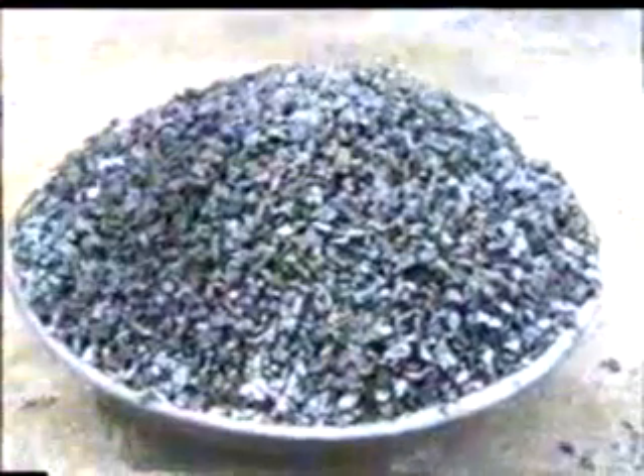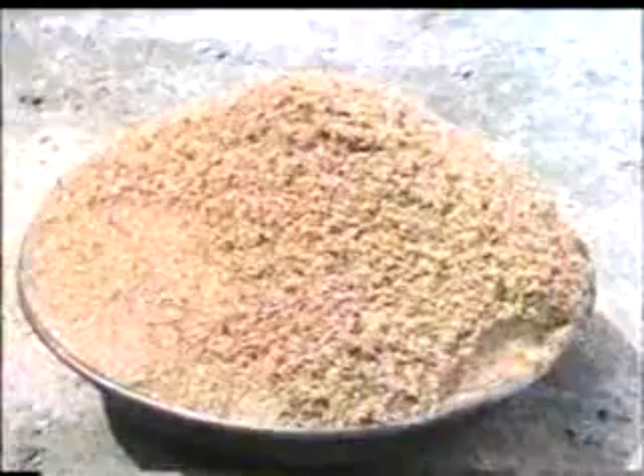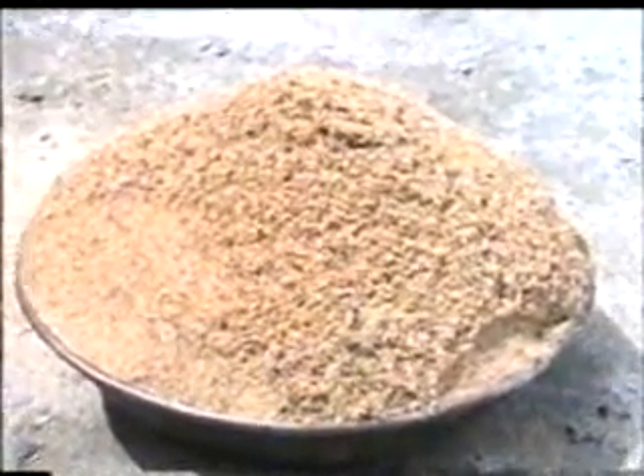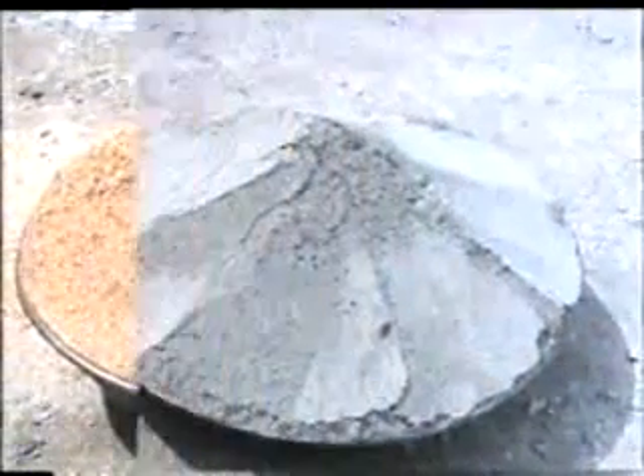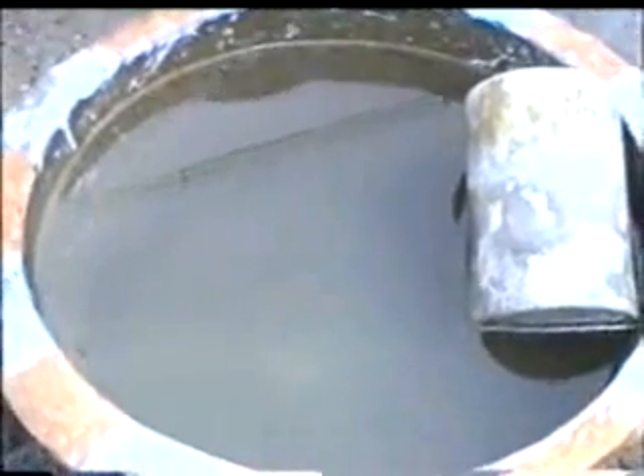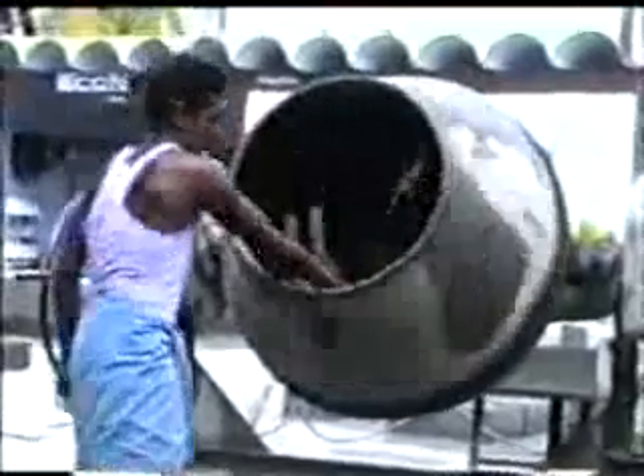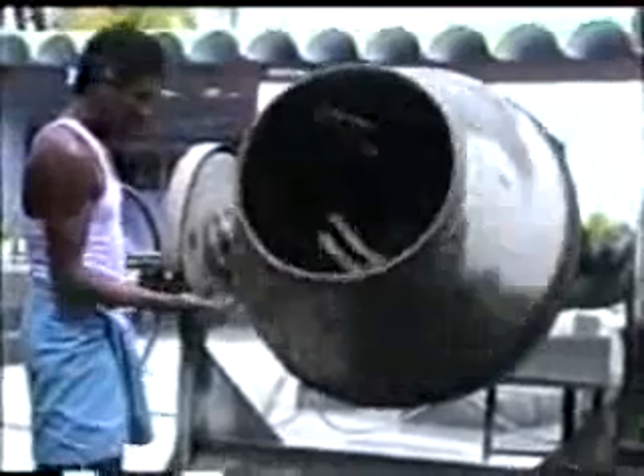Hollow block raw materials are chips, 8 to 12 millimeters, cement, OPC 43 grade, fine sand, and stone dust. The concrete hollow block production process involves four steps. The water to cement ratio is between 0.45 to 0.5 per kilogram of cement. For 1 cubic meter of hollow concrete block, 300 kilograms of cement is required, 0.45 cubic meters of sand, and 0.95 cubic meters of chips. The consistency of the mix should be such that it will cohere when compressed in the hand without trace of excess water.